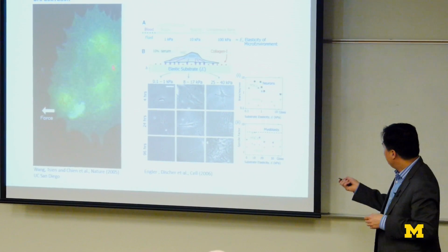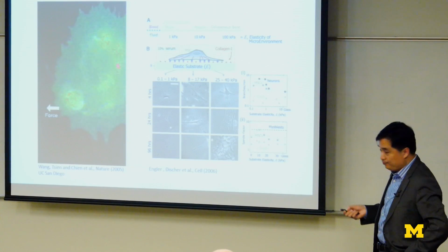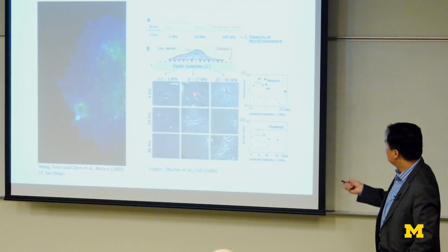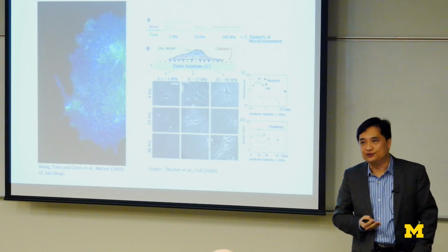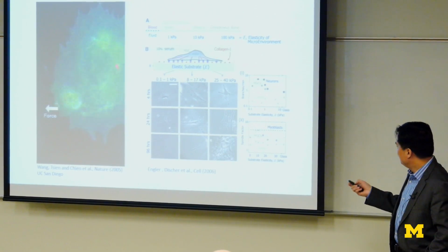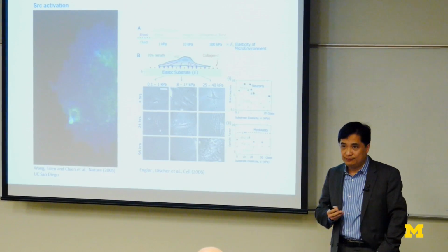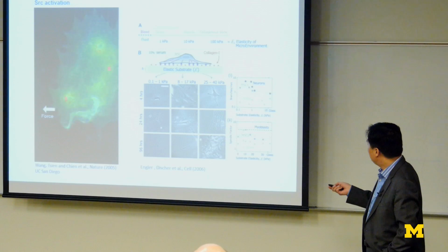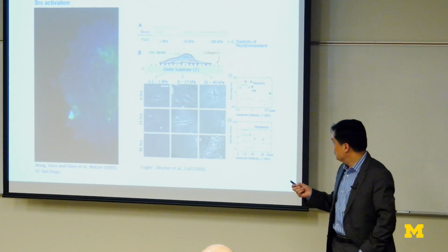On the other hand, in this example, the work done at UPenn, the Discher group, shows the long-term effects of mechanical signal. In this case, the elastic modulus of the substrate could regulate stem cell differentiation into different lineages, for example, bone, muscle, and neuron tissues. So all of these are related to the stiffness of the substrate. For example, on a stiffer surface, the cells may differentiate to osteogenic cells. On a soft surface, it could be adipogenic and elastic cells, or neuron cells.